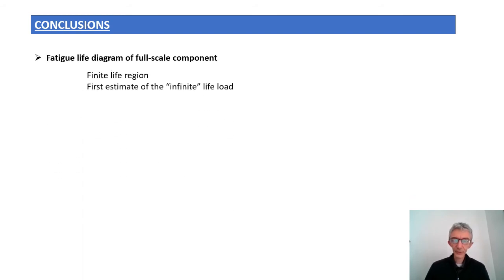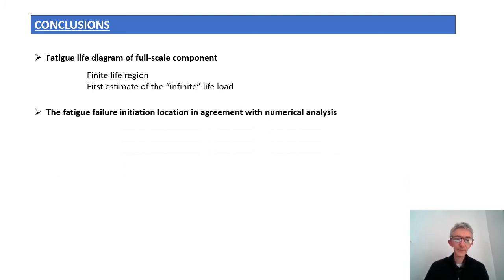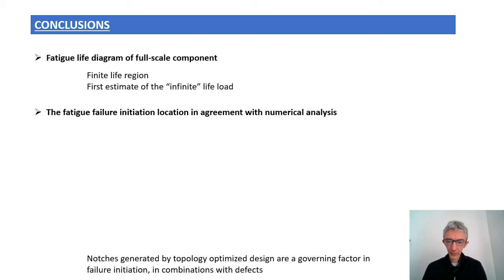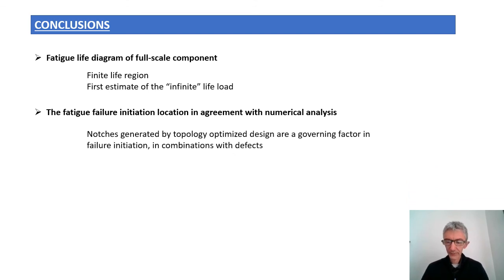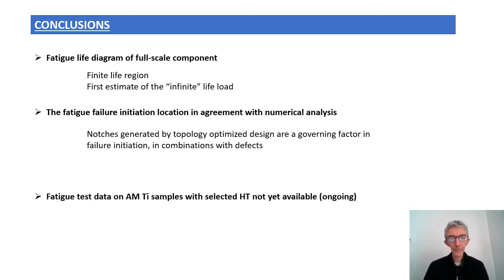So in conclusion, at this stage of the research, we have obtained our first fatigue life diagram of the full-scale components, which is quite an important result. And we have a finite element model that is in good agreement with the experimental analysis, so we hope in the future to use this model to better evaluate the effects of the notches that are generated by the particular geometry of the conrod.